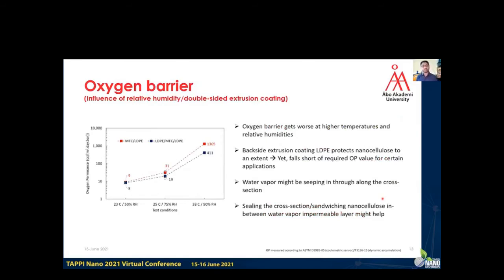And then moving on to the influence of relative humidity and double-sided extrusion coating on oxygen barrier. Here we have 3 conditions: 23 degrees Celsius and 50% humidity, 23 degrees and 75% humidity, and then 38 degrees and 90% humidity. For MFC and LDPE coating, the multi-layer structure is in red, and then the sandwich LDPE structure is in blue. So oxygen barrier gets worse at higher temperatures and relative humidities. Backside extrusion coating protects nanocellulose to an extent, yet falls short of required values for certain applications.